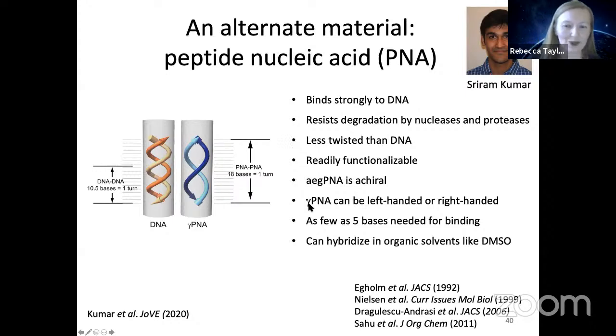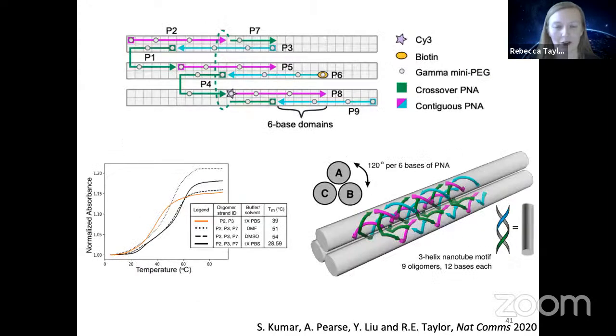It can also be left-handed or right-handed, which allows for some interesting computation opportunities. But really, it binds DNA, and it binds much more strongly to DNA than DNA does to itself, right? And then the final thing that's really interesting about it is it has no problem hybridizing in organic solvents. So there are these organic solvent mixtures that would typically lead DNA nanotech to come apart. This may not pose a problem for PNA, therefore expanding the range of environments where we can use structural nucleic acid nanotechnology.